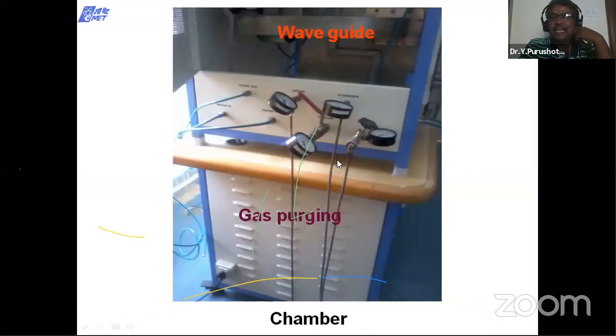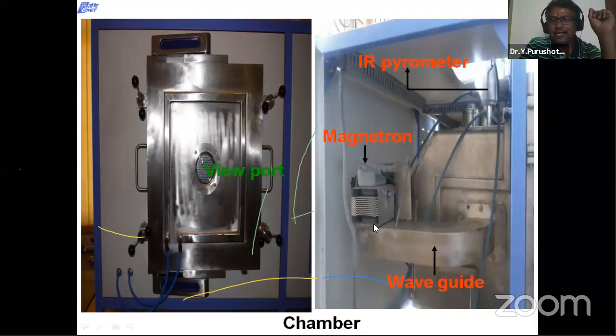And there is a gas purging facility also, for nitrogen and argon. Actually, we tried hydrogen, that was our aim, but there is a small air leak between this magnetron and waveguide. So hydrogen was coming out from this gap. Due to that we could not do it, because with hydrogen there is a chance of catching fire. So we could not do experiments with hydrogen, but we successfully conducted with inert gas.